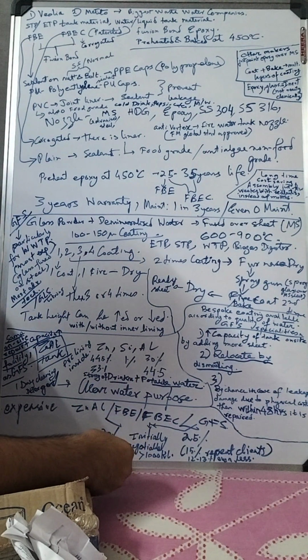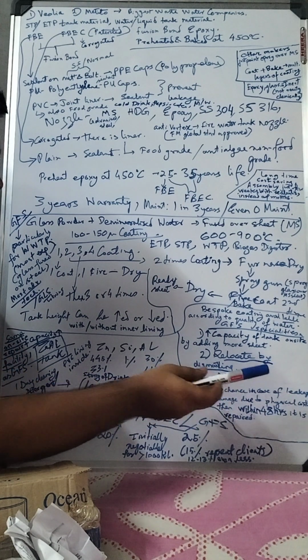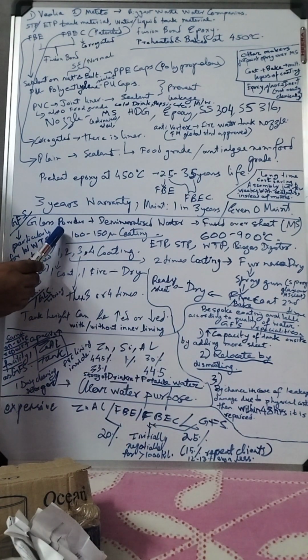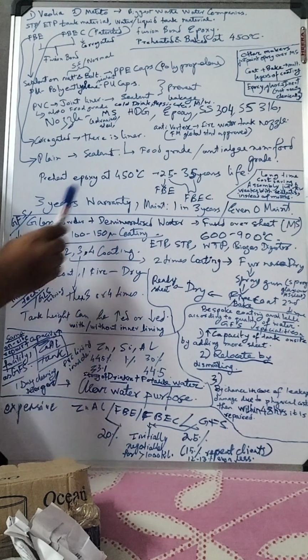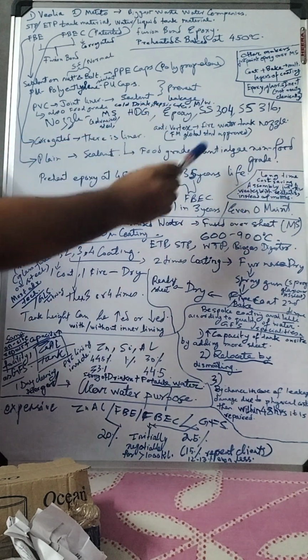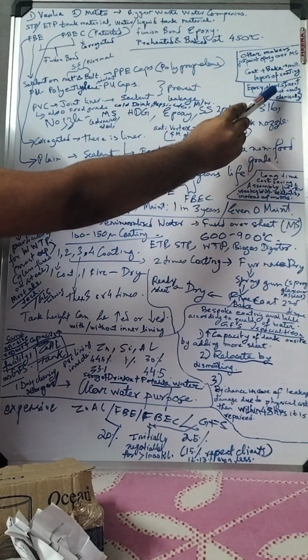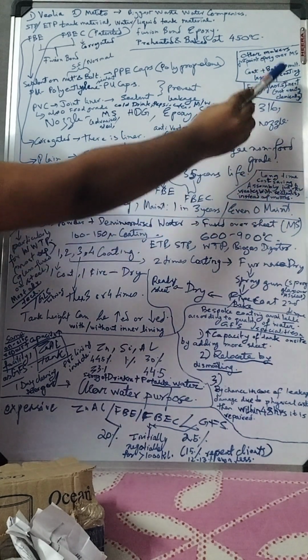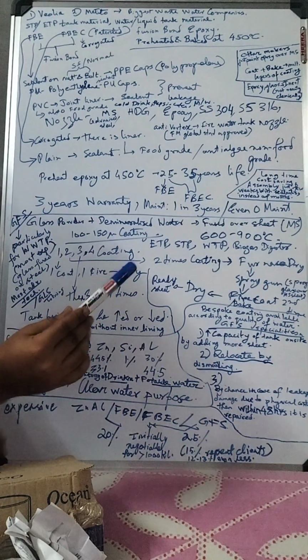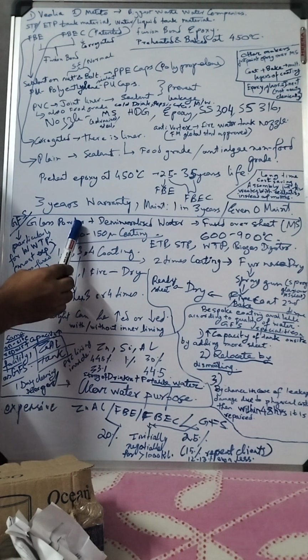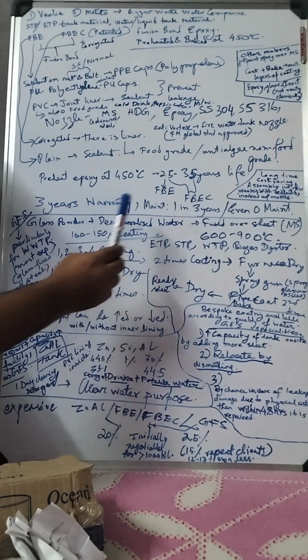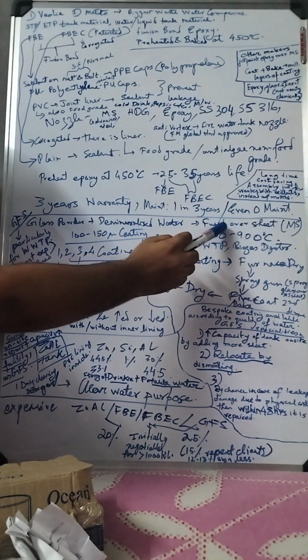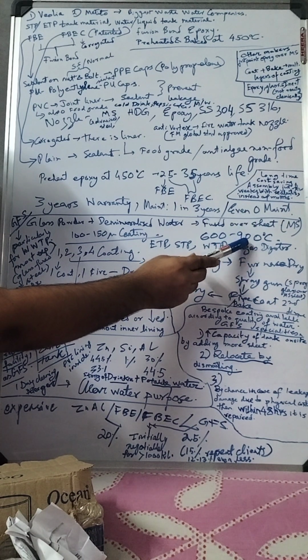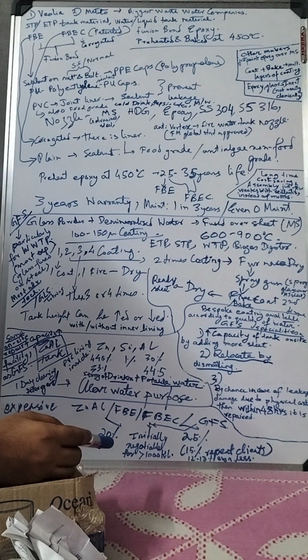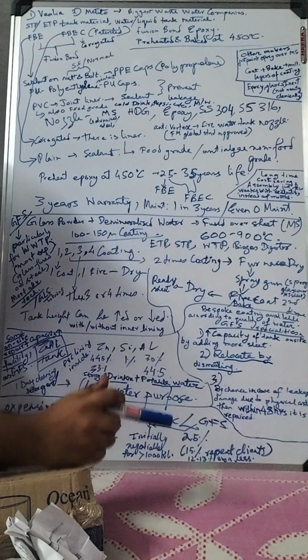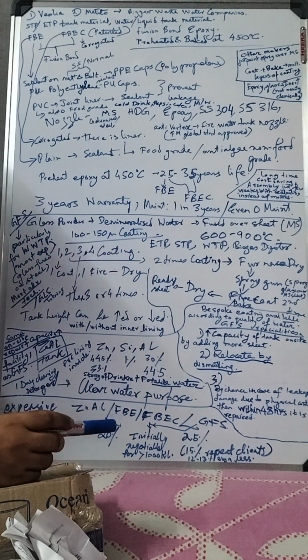And these three features stand true also for GFS. I told you GFS is the glass. Instead of epoxy coating, we provide glass coating over mild steel. Okay. Epoxy or glass coating over MS. So here also we do the same thing. We take glass powder and demineralized water, we mix them, and then these are fused over MS at 600 to 900 degrees Celsius. These are baked in an oven. Okay. Whatever thickness you want, 100 to 150 micron coating thickness, we are able to give.